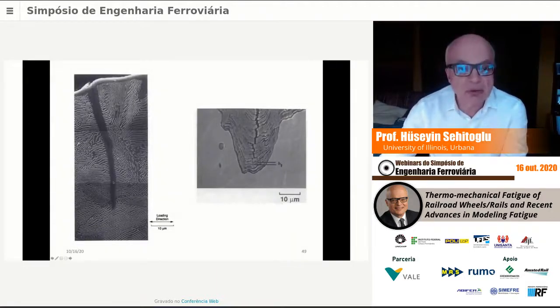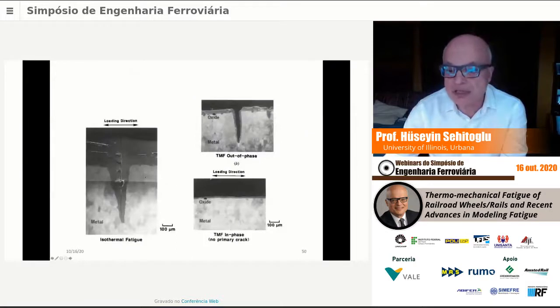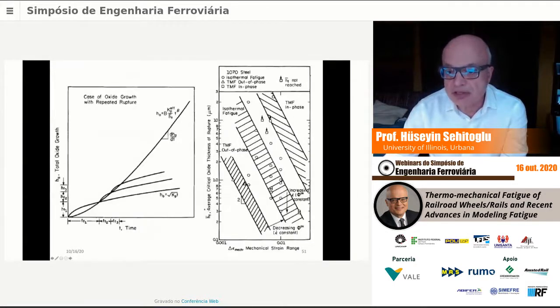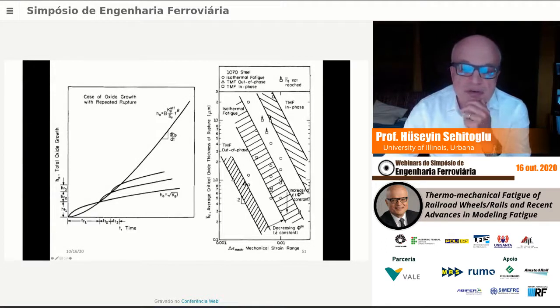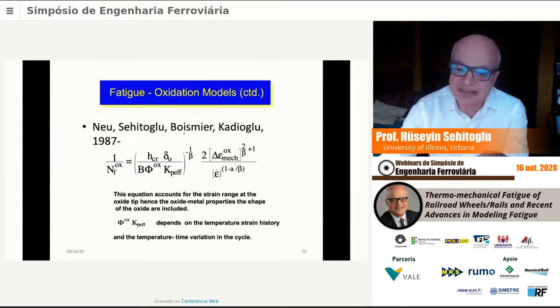But this was my earlier picture again. That's my oxidation case, that's the out of phase case. You could see the intermittent fracture of the oxide layers here, and that's how the crack advance occurs. And that's again the out of phase. This is the in phase case. We pointed out that these oxidation rates are not simply a function of time. We determined it to be a function of mechanical strain as well. So this is a bit like a Griffith criterion in a way.